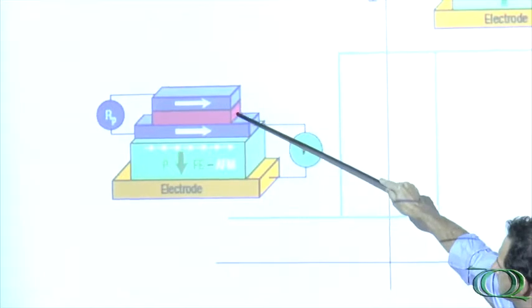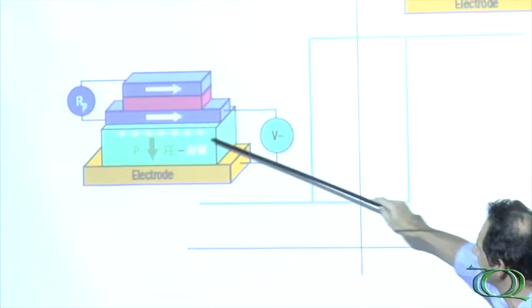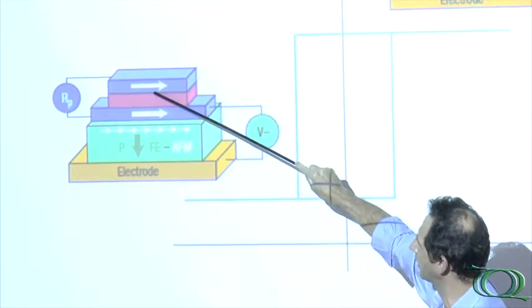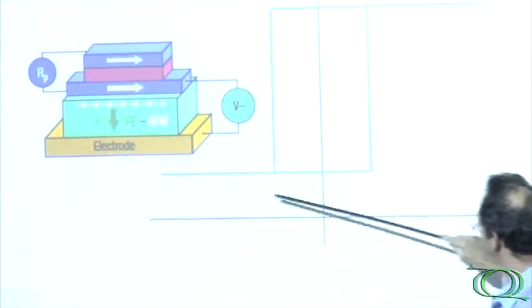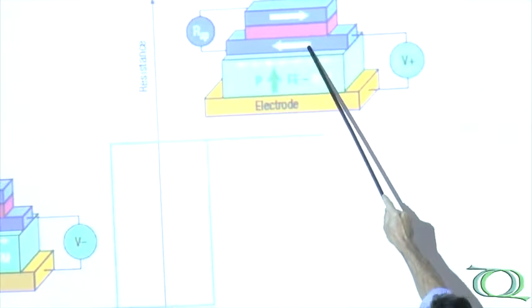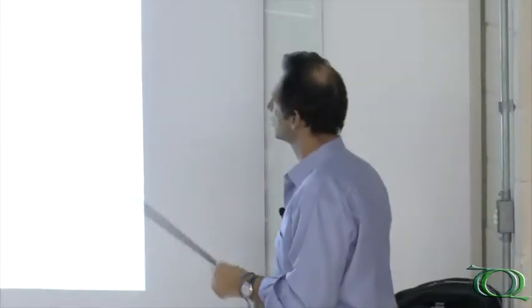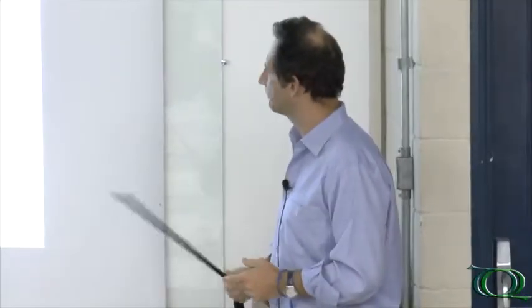And then you can use, but this is one possibility, this as a magnetoresistance tunnel junction, where if the top layer is polarized parallel to the bottom layer, the resistance is low. And if, on the opposite, the bottom layer is oppositely polarized with respect to the top layer, you have a high resistance state. And this is the advantage of being fast. The signal is large, and you have low consumption. This is a concept proposed by a laboratory near Paris, where also Albert Fert, the Nobel Prize winner who worked on magnetoresistance, has been working. And this is just one idea.